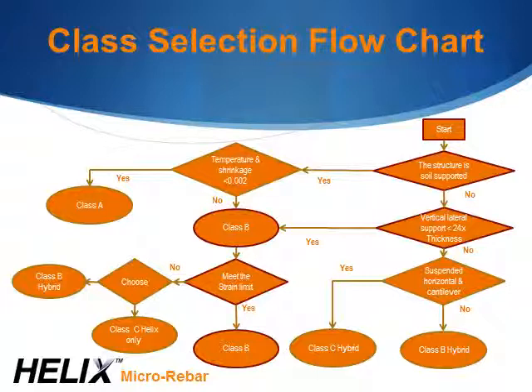Now, one of the things that is unique about the Helix design method is there is a tensile strain limit. If you remember back to those curves, I said that the Helix provides stable tensile resistance up to a point. Once it exceeds that, we need to provide some additional redundancy to assure that there's adequate ductility for the application. So when we do these designs, there's always a strain check involved. We're going to go to Class B design, but then we're going to do a strain check to confirm that the Class B design meets the strain check, which is an indication that there's enough ductility in that application, or whether it requires a different class of design or a modification in the design. All those details of the strain check and all the restrictions are in the evaluation report, and we take all those restrictions very seriously. It's very important that you review that document before designing with this to understand what they are.